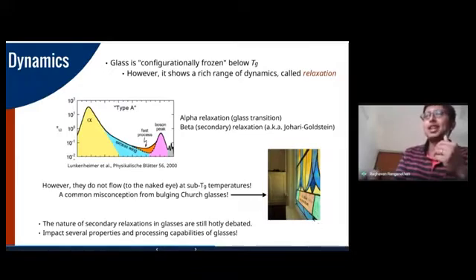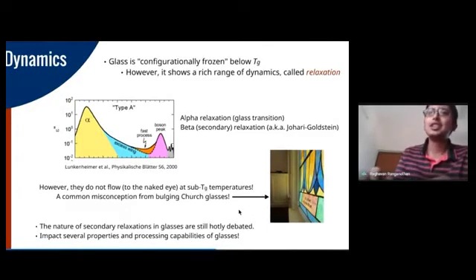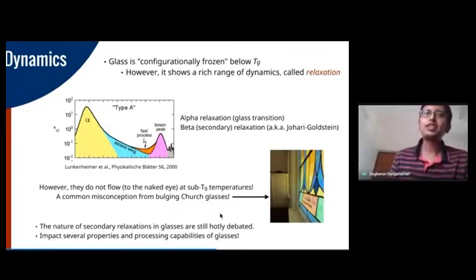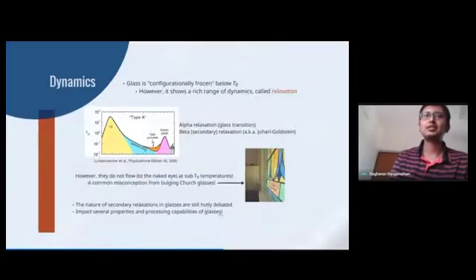That was an engineering problem. People did not cut the glass flat enough. For glass to actually flow and demonstrate a behavior like a liquid, it might take fantastically large times, maybe of the order of 10 power 20, 10 power 30 seconds or so. It might exceed the age of the universe. And that goes to show that glasses are quite stable in some sense, although they are actually metastable. And the nature of dynamics is still very hotly debated. There are several properties and processing capabilities that depend on these dynamics shown in glasses.